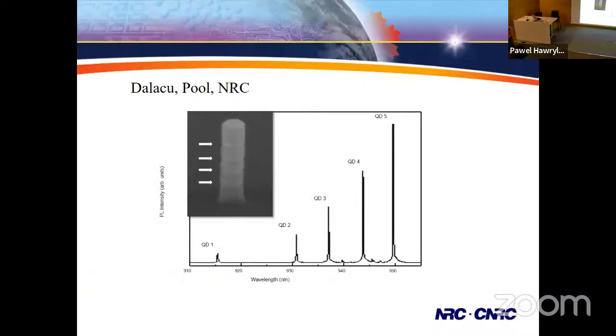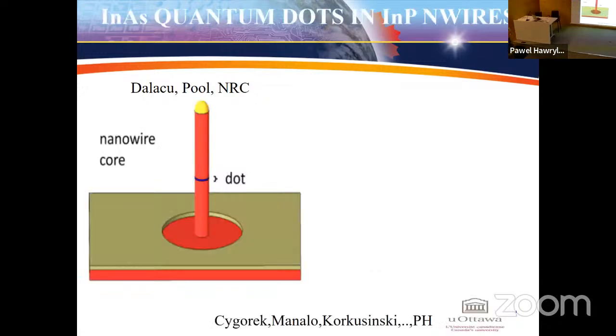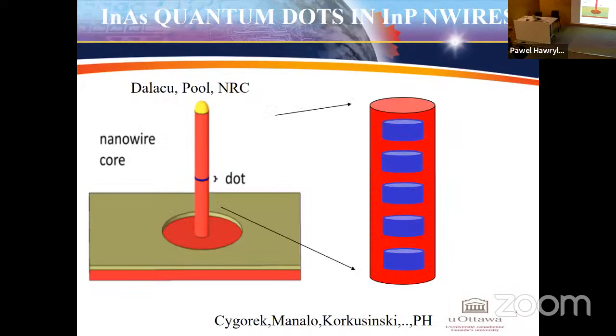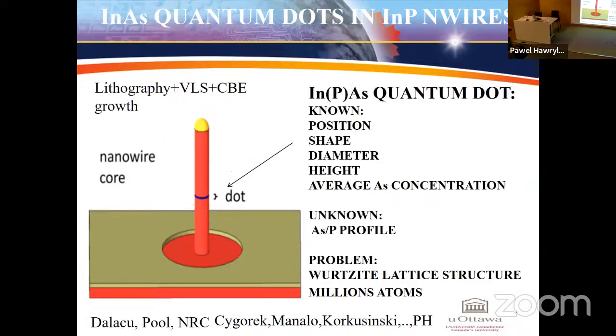This just demonstrates an ability to create an array of quantum dots. Here, each quantum dot is different, so that they have a distinct optical signature. All right, so we have a quantum dot, and we can generate an array of these quantum dots. The nice thing about these materials is that we know the position, the shape, the diameter, the height, and the average arsenic concentration. The arsenic replaces phosphorus, but we don't know the arsenic versus phosphorus profile. And also the problem is the Wurtzite lattice structure plus the size of our quantum dot. But this is a nanostructure about which we know a lot. Not everything, but a lot.